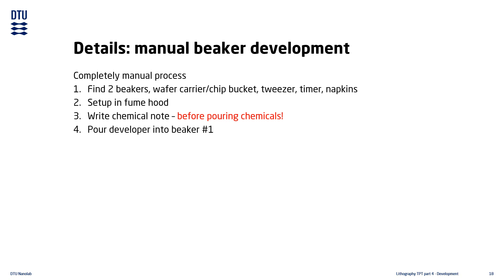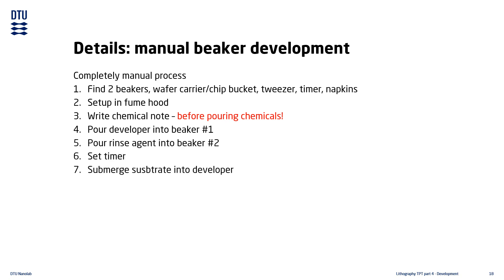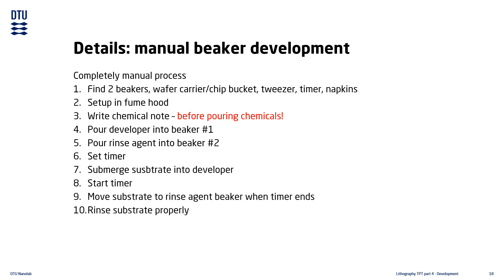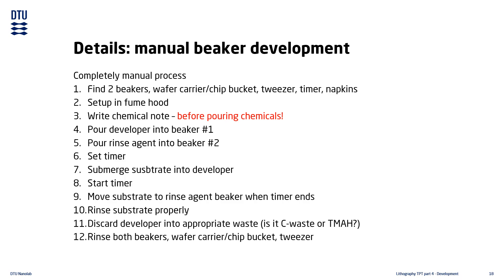Then you can pour your developer and rinse agent into the beakers and set the timer. As soon as you submerge your substrate into the developer, you start the timer. When the timer ends, you immediately transfer the substrate into the rinse bath — this stops the development process. Rinse the substrate properly, then discard the developer into the appropriate waste. Solvents go into the solvent waste drain, but TMAH goes into the dedicated TMAH waste can. Finally, you must properly rinse all the tools you used and clean up the fume hood.